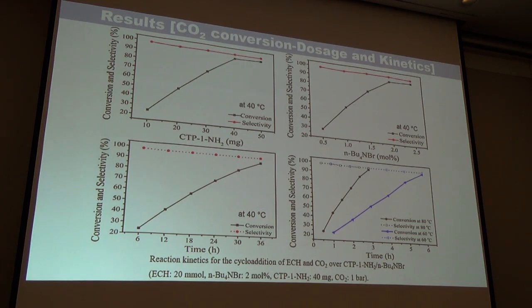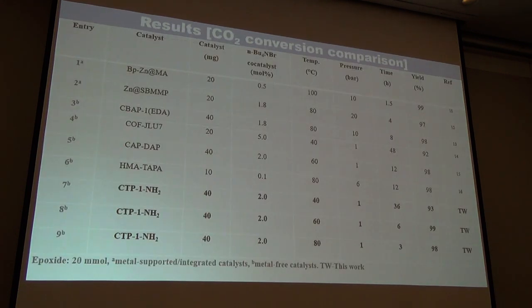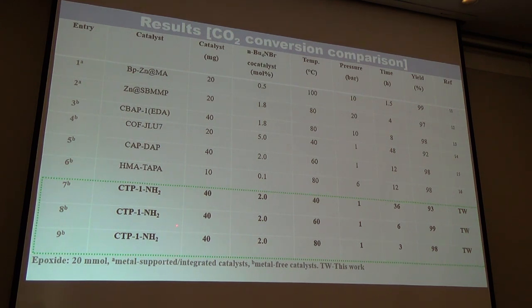in the product selectivity. Meantime, we have also tested the reaction kinetics at two other temperatures, such as 80 degree and 60 degree. At 60 degree, the conversion reached a maximum of 98% within 6 hours. At 80 degree, the conversion reached a maximum of 99% within 3 hours of reaction time. So the results were also compared with the previous reports, and the obtained results are quite good, and comparable with many reports reported previously.